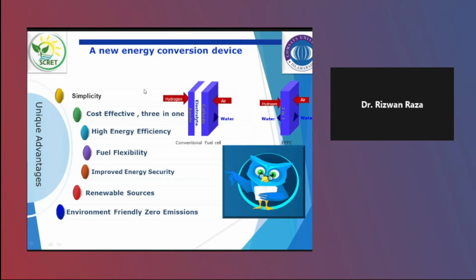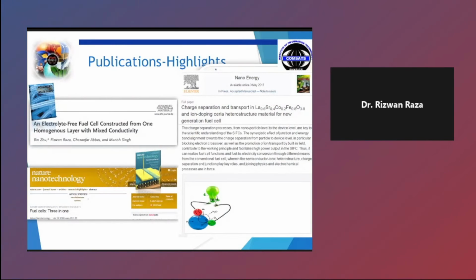So it has the same advantages as other SOFCs, and you can use hydrogen as a fuel and also other hydrocarbons like ethanol, methanol, biogas, and natural gas, as well as coal-based, carbon-based fuel. So in this, this composite material, we prepared in a single layer, in a single step, and we tested it. If you consider one page has two sides, one is the left side, the other is the right side. So one side can work as an anode, and the other side can work as a cathode. But in between, we can see there is some virtual layer which can work as an electrolyte.